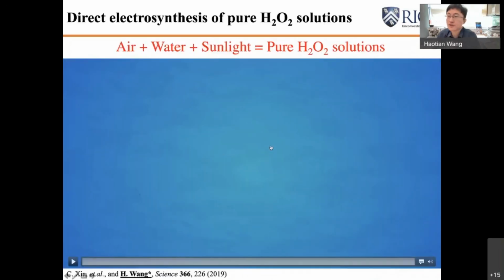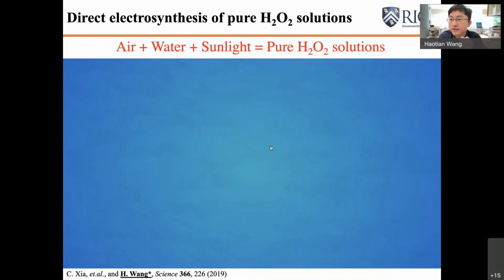Yes, an interesting story to share here in this experiment is we actually collected the rainwater from the Rice campus. We tested the total carbon contents in it. We call that TOC, which is the small organic carbon molecules in the rainwater. That's about 5 ppm. And we checked the handbook from the Texas drinking water standard. That needs to be below 2 ppm.